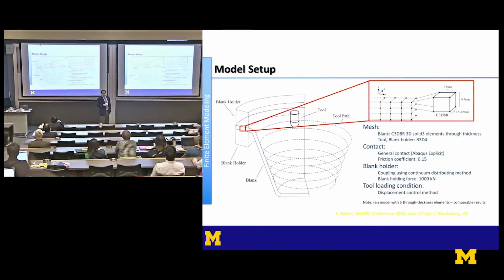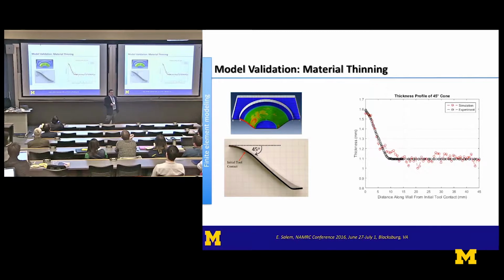We quickly set this up. There were others we teamed up with. By the way, we have a project going on with both Northwestern and Ohio State doing the modeling. The key is using very simple FEA tools. We were able to predict the shape and, more importantly, the thickness of the finished part. As you deform it, you stretch it, the thickness gets thinner. Here's a 45-degree cone, and you can see the model very nicely predicts the thickness and shape of the part.